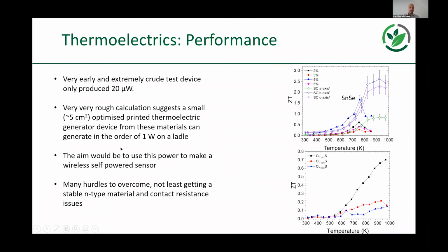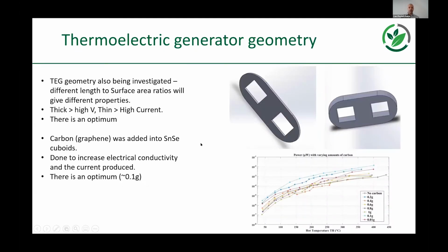What's interesting about this, and this relates to the opportunities that Sridhar highlighted, is that we're able to potentially produce self-powered sensors, which would allow us to track the temperature, for example, of a ladle as it goes around the steelmaking process, which could be driven into some of these data-driven innovation approaches to look at better thermal scheduling, for example. And the nice thing about them is that they have nice efficiency peaks, which are a function of that Seebeck coefficient and thermal conductivity, the ZT value, that correspond nicely to what our ladle shell temperatures are. So we're looking at that as an immediate opportunity.